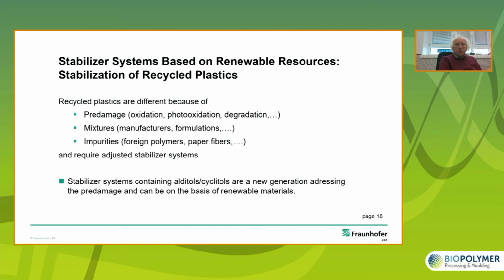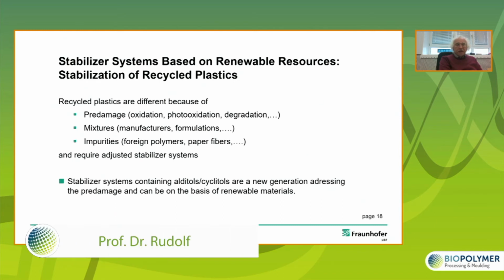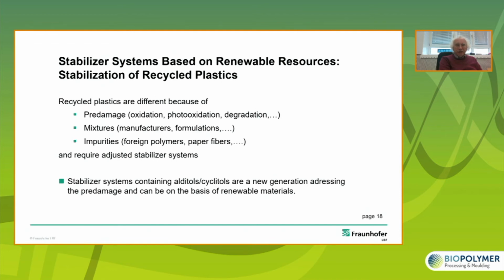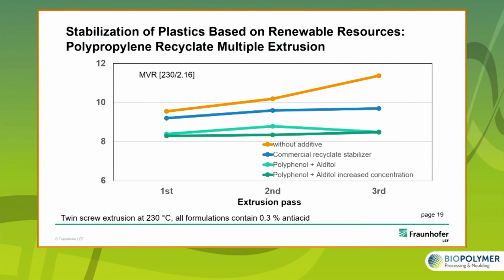A stabilizer system, which is not identical, especially in cost performance, with the stabilizer system normally used for new material. And here we could prove that the stabilizer systems based on natural phenols plus alditols and cyclitols are able to address pre-damage, and as I said, here for the first time we have the possibility to use renewable materials, 100% renewable materials. In this case, it's a multiple extrusion, and here we measure the melt flow, 3 extrusion passes. The more stable and the lower the melt flow, the better the processing stabilization.